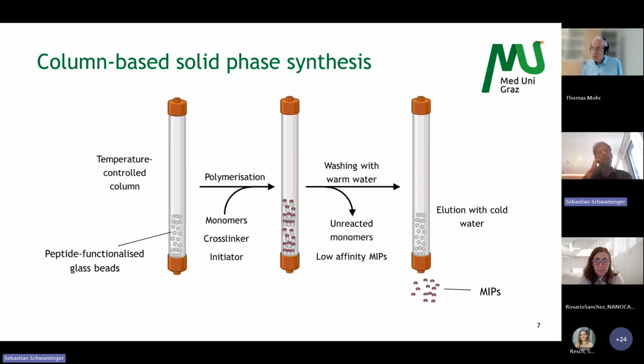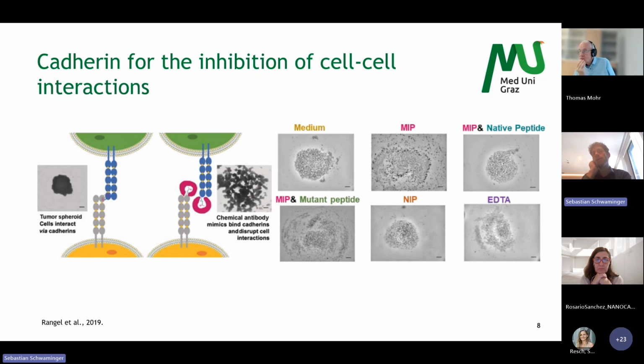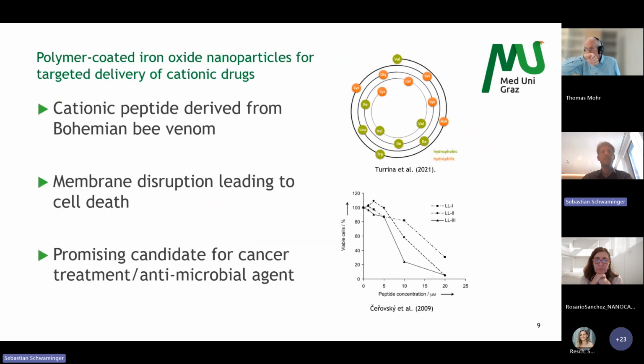Therefore, we have a column-based solid phase synthesis. So basically, we can automate our synthesis. We use glass beads, fill them in a column, put our receptors there, and polymerize them with cross-linkers, and get our molecularly imprinted polymers out by thermal elution. This is one classical peptide receptor for which we've done that, cadherin, for the inhibition of cell-cell interactions. This is a typical epitope on multiple cells, which we tested here.